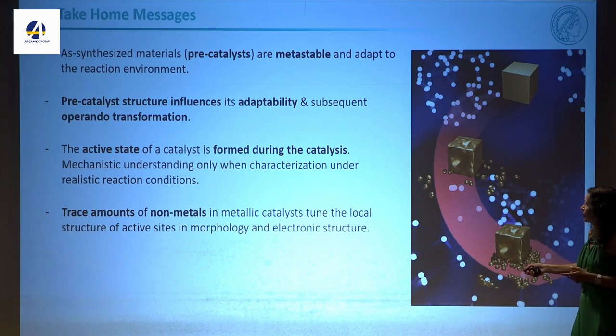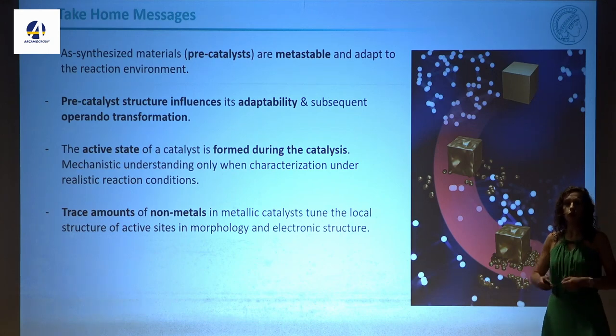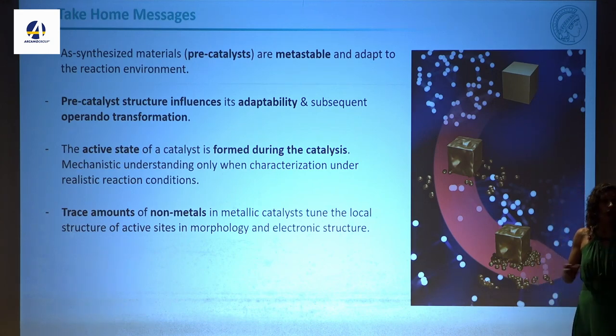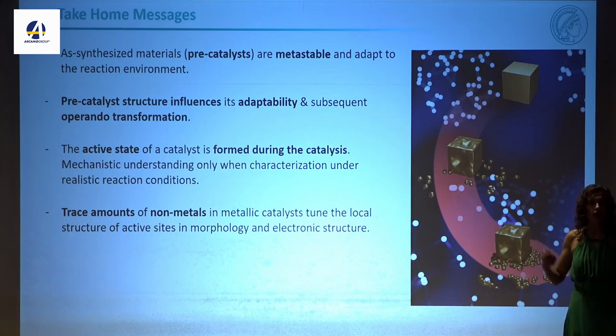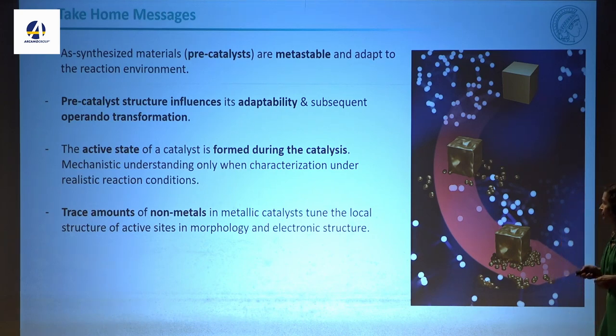Trace amounts of non-metals in metallic catalysts tune the local structure of the active sites in morphology and electronic structure. This could be oxygen, this could be carbon incorporated into the material. We could get things from the electrolyte, for example, iodine that we are using in these electrolytes. All of these are going to be part of your catalyst and are going to influence your performance.